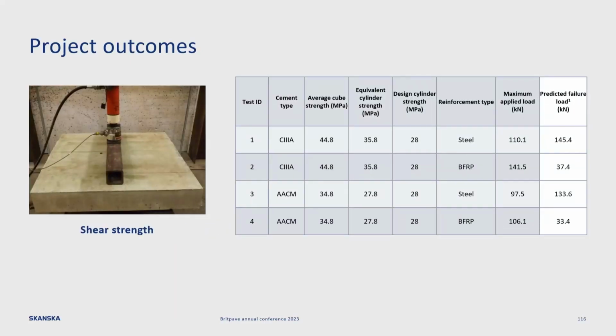So for shear strength, these were even more interesting, because if you take the pure shear value of basalt fibre reinforcement, it's not very good. And it's very difficult to use design codes to design a structural member using the shear values that you will find for pure basalt. It's not a homogeneous material, it's a pultruded construction method, so all the strands are laying in one direction. You could basically cut through them quite easily with a knife compared to steel. So currently, without the codes and standards, it's very difficult to design using basalt.